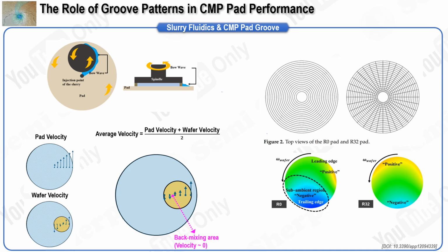This issue is clearly observed in the case of the R0 CMP pad, which features grooves only in concentric positions without any grooves in the radial direction. In this back mixing area, slurry cannot flow in easily, and the byproducts from the polishing process are not expelled effectively. Consequently, the surface temperature in this area rises, leading to poor material removal rates and suboptimal planarity across the